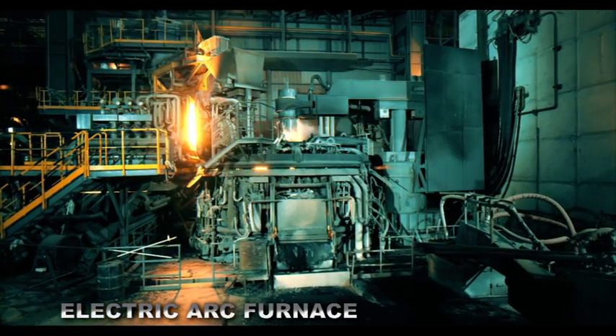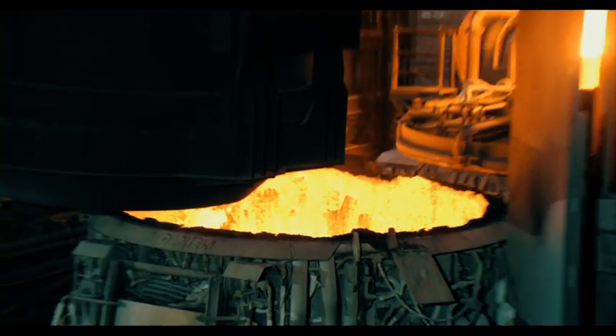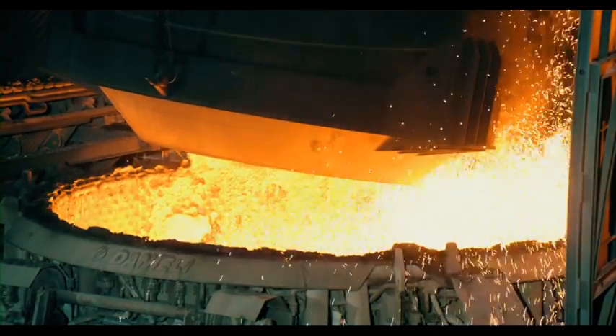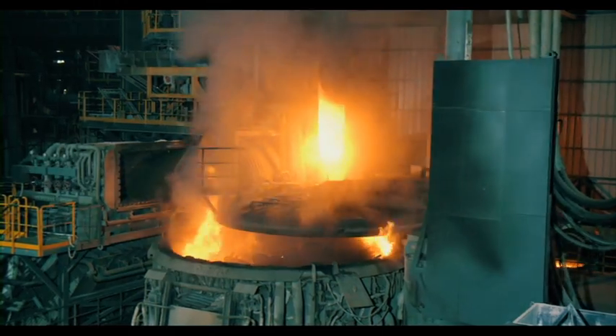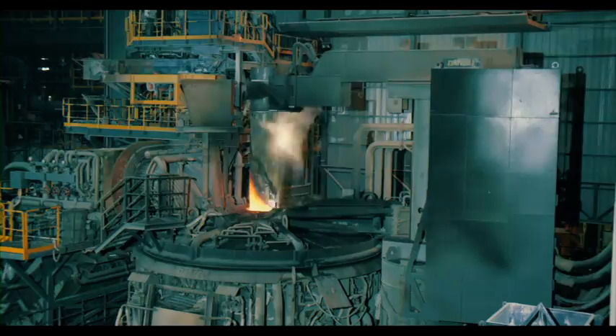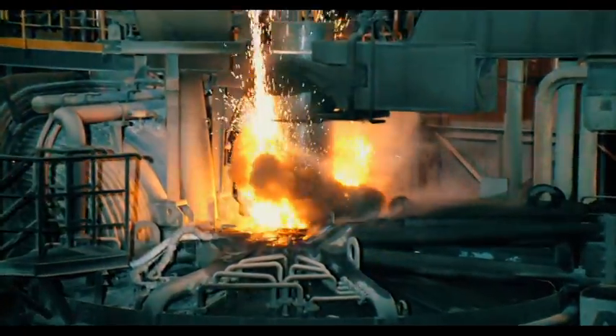In the AKS plant, there are two electric arc furnaces. At the beginning of the melting process, scrap is charged through the opening of the preheated arc furnace. Electric arcing begins after closing the lid. A graphite electrode is used for arcing, which generates heat that melts the scrap. At this stage, lime, HBI, and dolo-lime are gradually added.